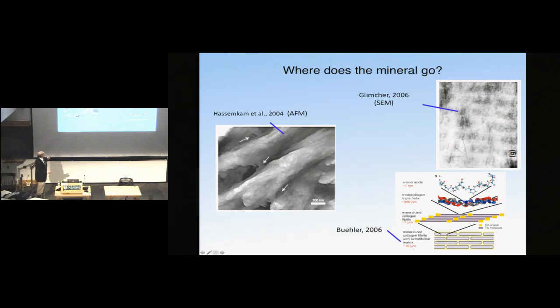The AFM community says, well, the way the TEM images are obtained is by taking bone and crushing it in a mortar and pestle. And so of course, that's going to knock off the mineral. But the TEM community has the argument that, well, what's being done here is an AFM in tapping mode. And yes, if you have rocks in Jello and you tap the Jello, you're going to feel the rocks, and the Jello is just not going to show up.